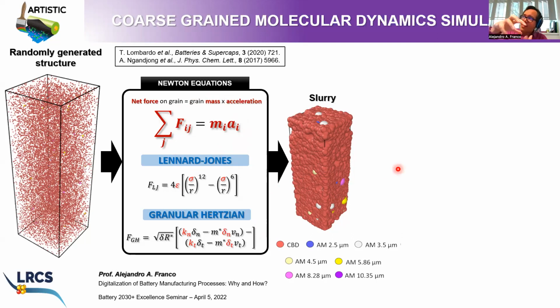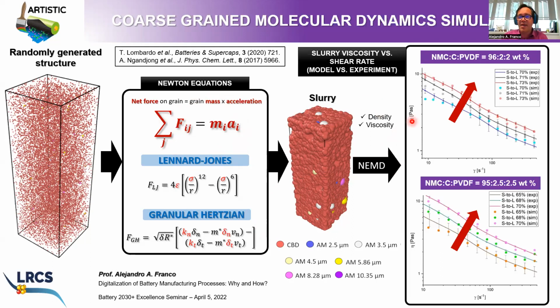Once you get this virtual slurry microstructure in the computer, then you can characterize it in terms of the density, in terms of the viscosity, and then you can compare the numbers that you get in the computer with the ones that you can characterize at experimental level. And here you see examples for the viscosity calculated as a function of the applied shear rate for two different slurry formulations and for different solid contents, right? And you see here a very good comparison of what we calculate with the model with what we can get at the experimental level, right?